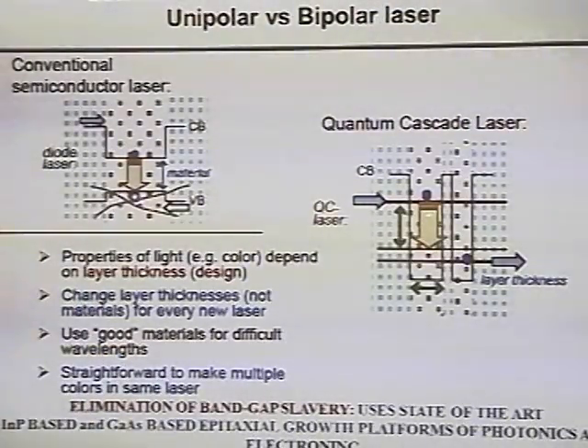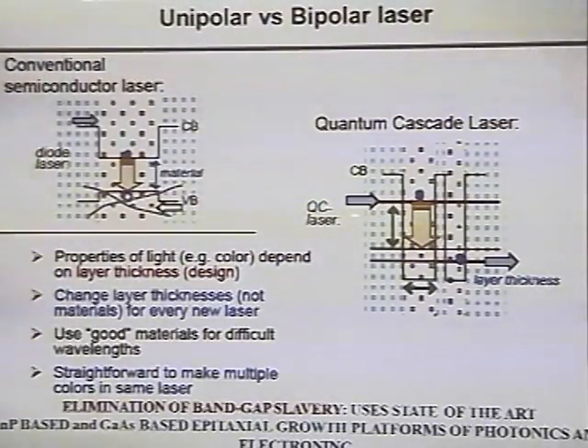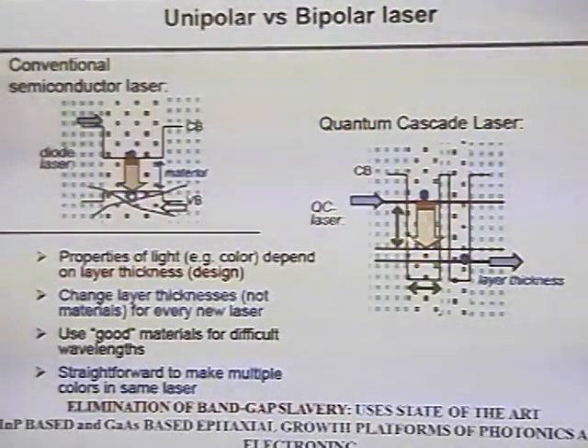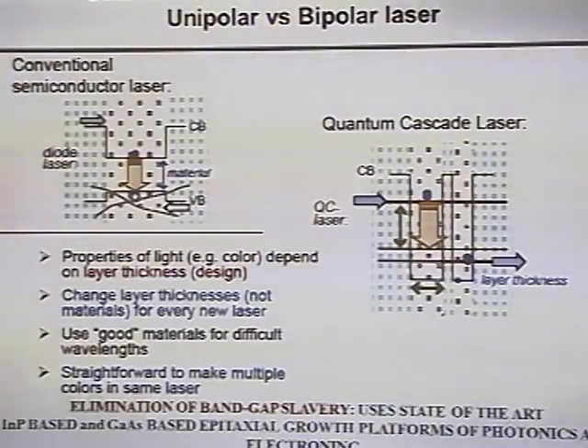This is an optical transition that occurs within the conduction band of a quantum well. These are quantized levels that form when I make ultra-thin layers of the order of the de Broglie wavelength. Then I form energy levels. And using another quantum mechanical process, tunneling, I can now lase, if I invert the population across these two states. Now here you understand the tailorability immediately. If I make a deep enough well so that I can accommodate many photon energies, then using the same materials, this band gap and this band gap here, and just changing the thickness, I can tailor, in principle, the wavelengths from, let's say, a few micron, 3, 4 micron, up to maybe 300 micron.